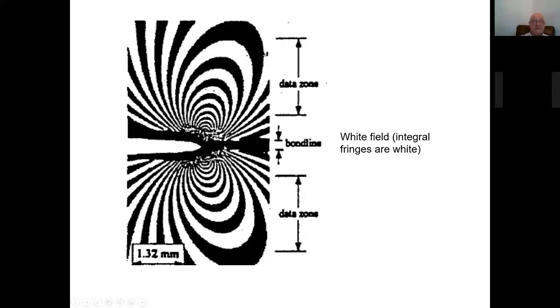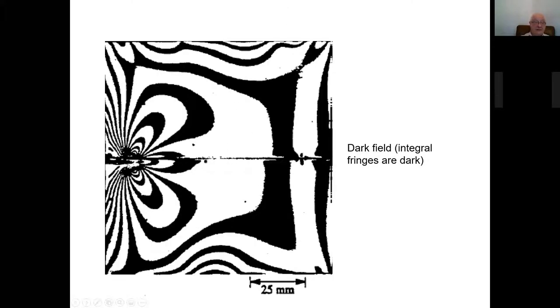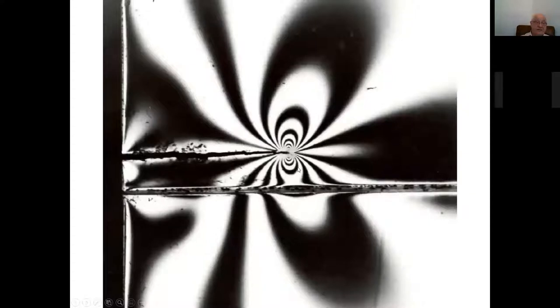Here you have a white field. Essentially, it doesn't really matter if it's a white field or a dark field, you should just know this, but the important thing is that you have to go further away. If you have cracks which are parallel to bond lines, as you can see here, the fringe pattern is quite disturbed by the bond line, and it depends very much on the distance from the crack tip to the bond line. So this type of measurement is not very simple, and you need to have accurate measurement of the distance from the center of the fringe to the tip of the crack.